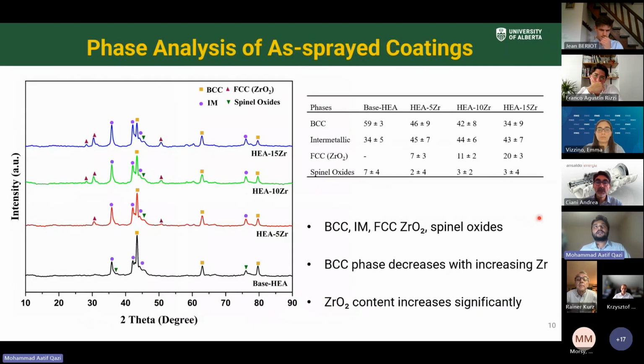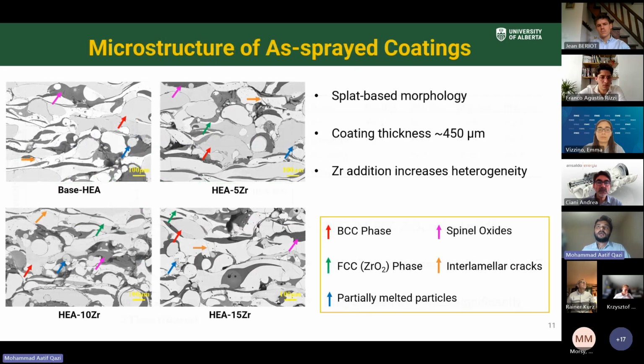Here is the XRD analysis of the coatings, which shows 4 phases, namely BCC, intermetallic phases, FCC phase, and spinel oxides. So as the zirconium percentage in the coating increases, the BCC phase decreases, and the ZrO2 content increases in the coatings. The SEM microstructure of the coating shows splat-based morphology with the coating thickness around 450 microns.